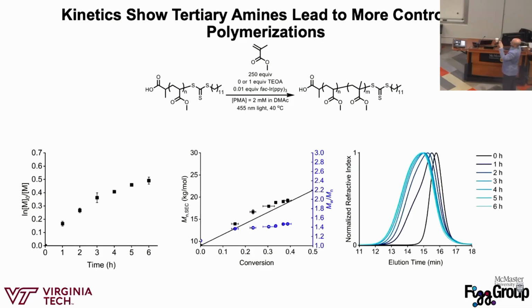This is really exciting because in the single unit monomer insertion paper that I talked about, we could get predictable molecular weights, but it was just based off monomer concentration. Now we can look at conversion versus molecular weight. Predictable molecular weight is one of the things that we want for controlled polymerizations. And what we see is we actually get pretty linear increases in molecular weights.